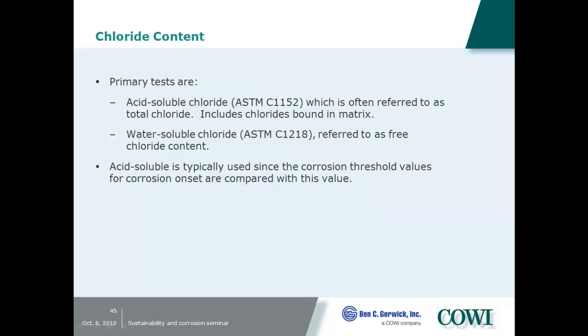As I said earlier today, what causes corrosion is the water-soluble chlorides, but they are extremely difficult to measure. Actually so difficult that we normally don't do it. We measure the total acid-soluble chloride concentration and use that, where we have rules of thumb for what the threshold values are.